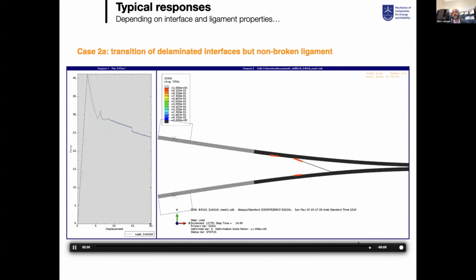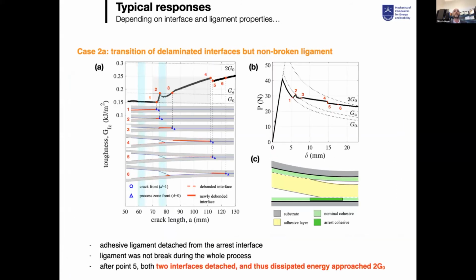So of course, the immediate consequence of this is that you increase a lot the apparent toughness. Your P delta curve, instead of being here, is going to become very flat like this with a toughness that is going to increase when the crack is extending. That means your crack propagation is becoming progressive because you have this increasing R curve. So here you start to see the path towards engineering the microstructure and controlling the response to crack propagation of your interface. So of course, this mode of delamination depends on how much your ligament here is going to survive,